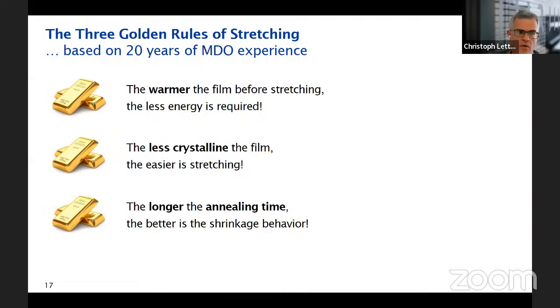If you look at the solutions in the market, basically everybody is building a nice MDO line. These are available in the market. Three things are important. If you stretch film, the film should be warm, it should be an inline process. The warmer the film when entering the MDO, the easier it is to stretch. It should not cool down too much, because if it cools down too much, crystallization is going on, and stretching becomes more difficult. And there should be a certain time, as long as possible, before the film meets the winder, because this positively plays on annealing time, and the longer the annealing, the lower the shrinkage will be later on, which is important for the sealing process.